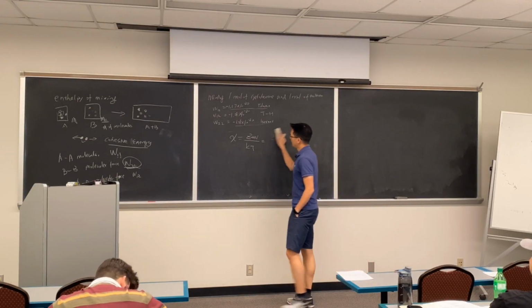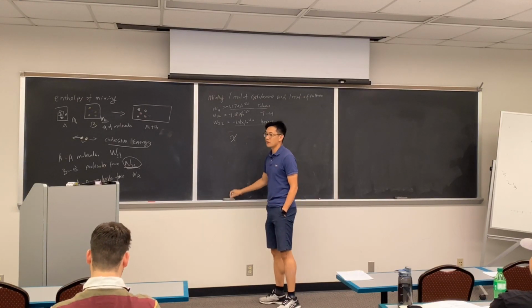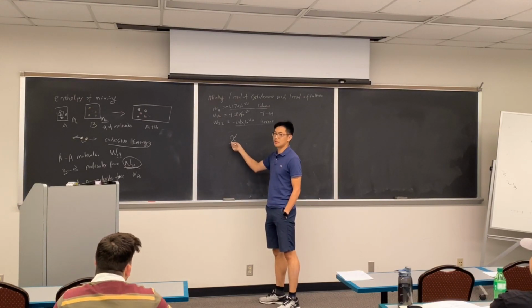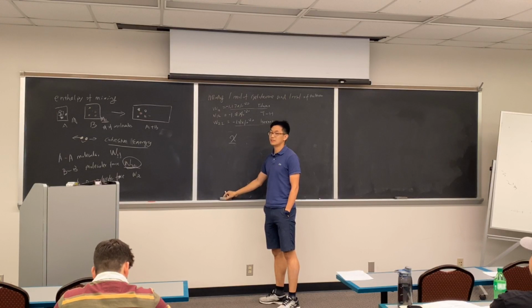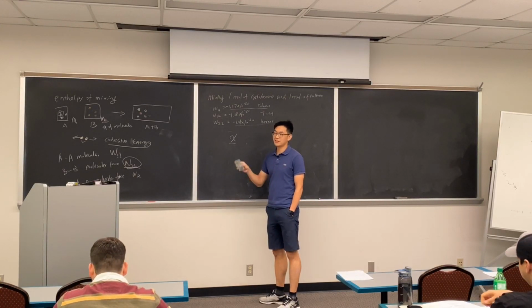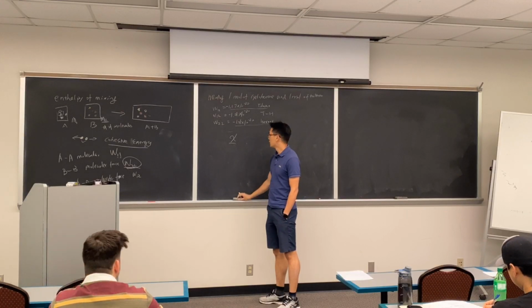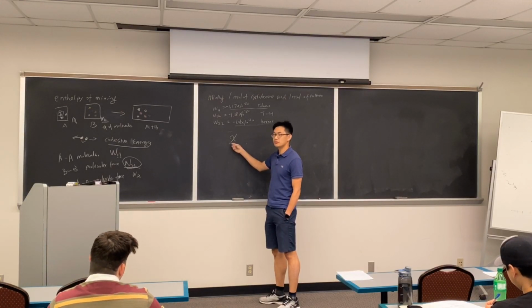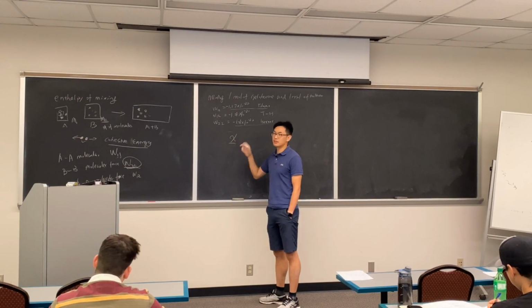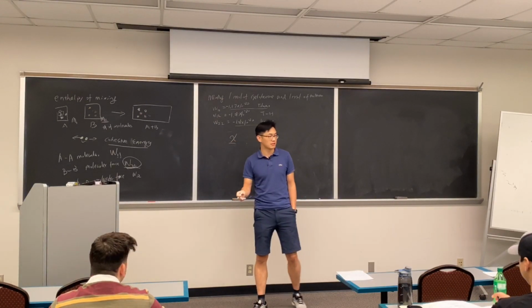Does it make sense? This is how we actually apply lattice theory to know if your molecules will mix or not mix. But one of the tricks is you have to look up the chi parameter. This is in the Polymer Handbook. You can search any two combination of materials. If you don't know, there's also an empirical equation linking the solubility parameter with chi. If you know the solubility parameter, you can calculate what the chi is.